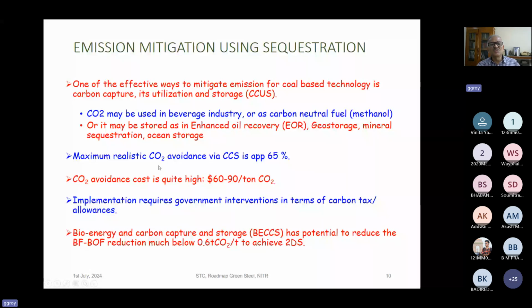Okay, so you have some realistic CO2 avoidance that is around 65%. You cannot do 100% reduction because the equipment that will be used for CO2 capture and all these things also involves a lot of carbon. That is the energy, and if that energy source is carbon, then it also emits CO2. So CO2 avoidance cost is quite high today. It is around $60 to $90 per ton of CO2. So it is not easy to take up CO2 sequestration.